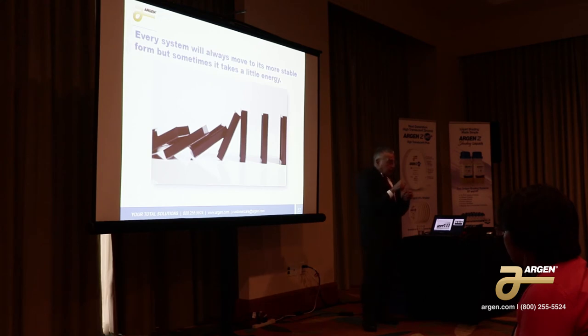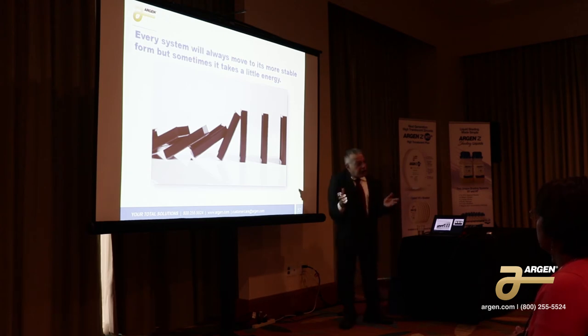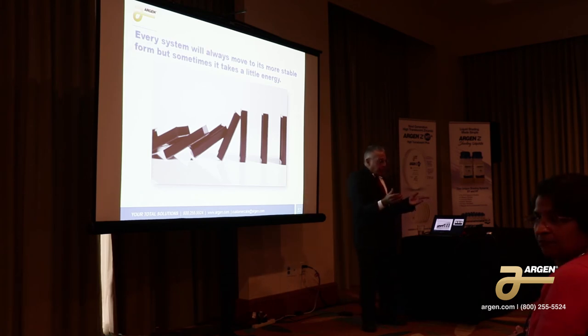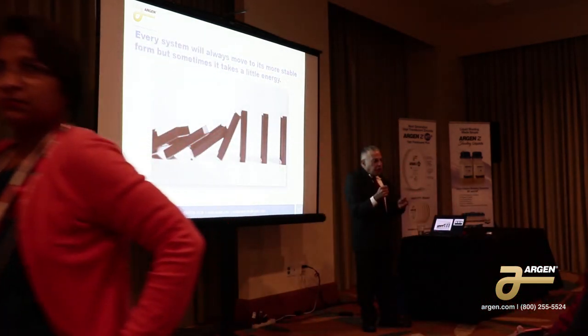That's what happens when the dentist gets a hold of it — if we don't use water when they adjust a contact, it'll fracture. If you see sparks, you're witnessing the marvelous transformation of zirconia from tetragonal to monoclinic. Because it's going to a lower energy form, and the sparks you see is a manifestation of the excess energy. But you don't want to see sparks. The dentists have to know to always adjust with water.